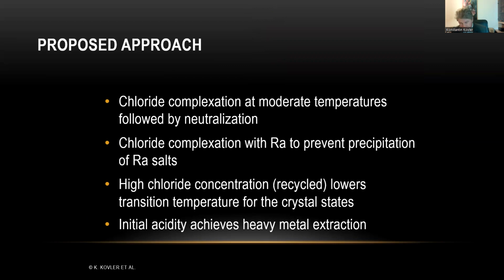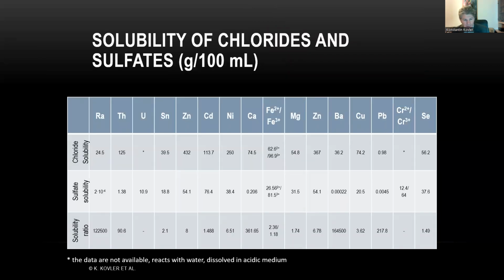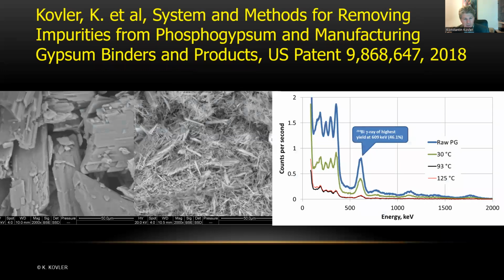By the way, high chloride concentration is the agent, which is in our case calcium chloride, but it's in recycle, so we don't consume too much of this agent. This is a very cheap agent, by the way. You can compare the solubility of chloride and sulfate of radium, several orders of magnitude. So the task is how to move from insoluble, practically insoluble radium sulfate to soluble radium chloride, and then how to filter it, how to get rid of this radioactivity. And it was done by a complex treatment based on thermal, but not under high temperatures. Look at the temperature on the right side of the slide, and phase changes, and also agitation. It means a complex mechanochemical treatment. It's a part of our patent.